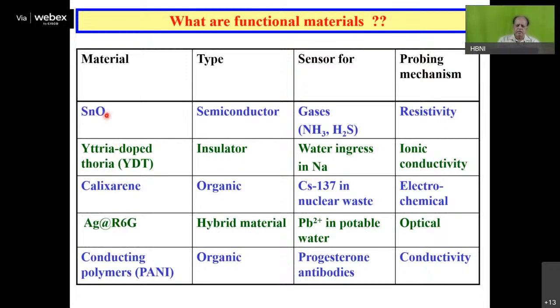For example, tin oxide is a semiconductor. It is used to develop sensors for toxic gases like ammonia and H2S in air. In this case, resistivity of tin oxide is measured, which translates into the concentration of ammonia or H2S in air. Next is yttria-doped thoria, YDT, an insulator. In this case, we measure ionic conductivity, which gives us the value of sodium in water. It is used in fast breeder reactors.